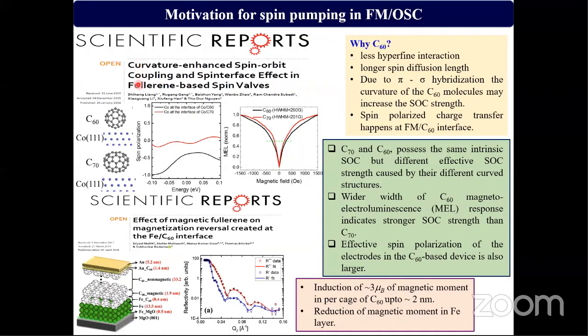In this Scientific Reports paper, they have observed curvature enhanced spin orbit coupling and spin interface effect in the fullerene based spin valve. They have taken C60 and C70 molecules, and both the spin polarized and MEL data showed that the spin orbit coupling strength is more for C60. It has also been observed that spin polarized charge transfer happens at the ferromagnet C60 interface. In this paper, when C60 is deposited on top of iron, at the interface around 2 nanometer of C60 becomes magnetic, and it exhibits nearly 3 mu B per C60 magnetic moment.